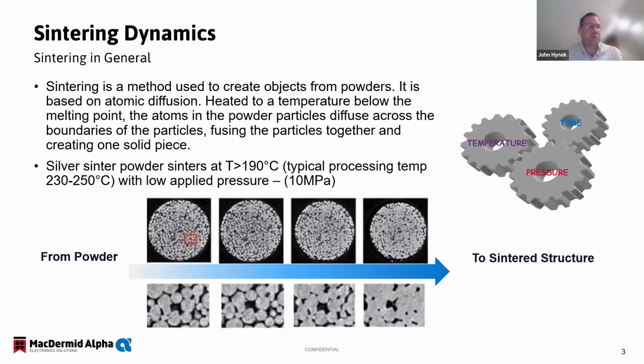The difference between sinter paste and solder paste is that with a sinter paste, there is a step of sintering, obviously, which you do instead of the reflow profiles that you would use in soldering. So the sintering process requires temperatures usually above 190 C with low applied pressure, usually around 10 megapascals, for a certain amount of time, which can be upwards of 5 minutes or so.